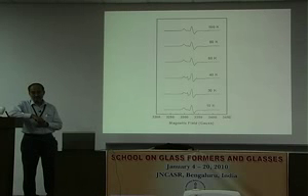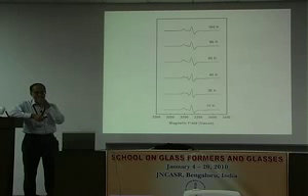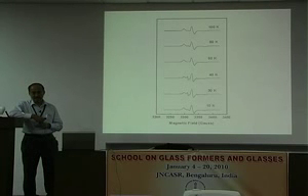No, there is a little bit more than that, because the signal that has been attributed to the glass transition is attributed by Austin to a relaxation effect, which happens. The results of Johari and others you are referring to. No, I mean, what is standard is that if you cool a liquid down at a given rate, it undergoes a glass transition. If you warm it up at a higher rate, it begins to relax below the glass transition temperature that you measure, and this is going to have a calorimetric signature.